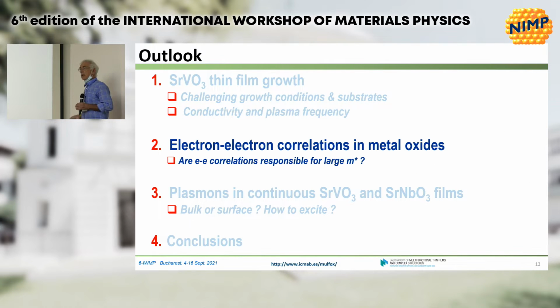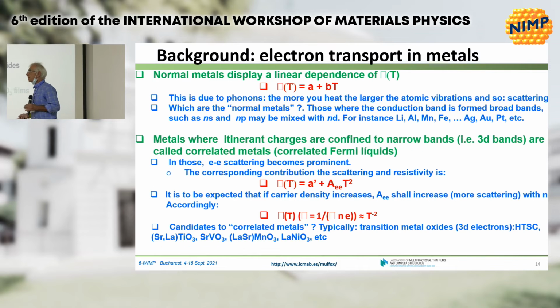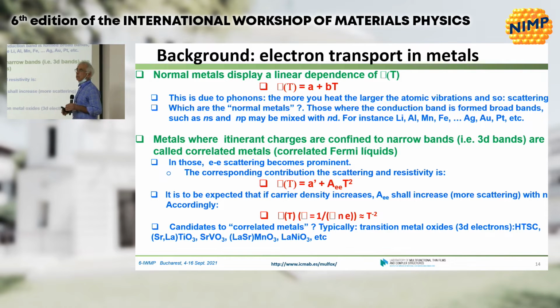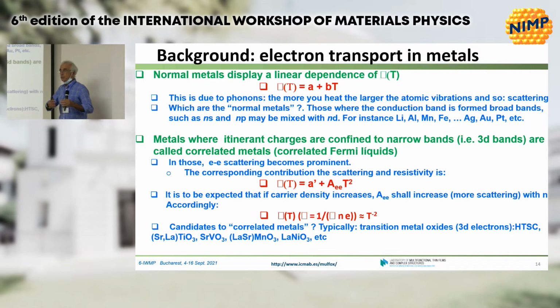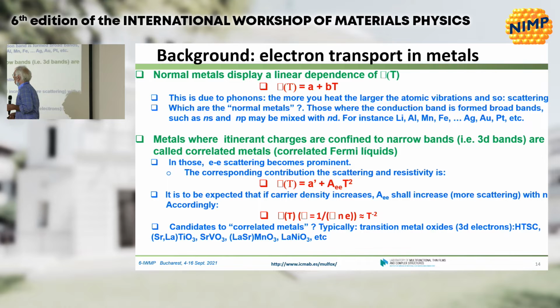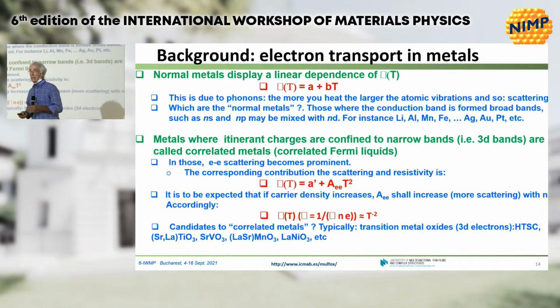So let's go now to the point of electron-electron correlations. The easiest way to identify the role of correlations in a metal is to measure the resistivity. You know, the resistivity in a normal metal is typically linear with temperature, and that is related to the excitation or the scattering with phonons in the system. If you have in this metal a huge number of electrons with a lot of scattering among them, then you don't have this term, BT, but you have a term which is T squared. This T squared is proportionally related to the scattering among electrons. This is typical of correlated metals.